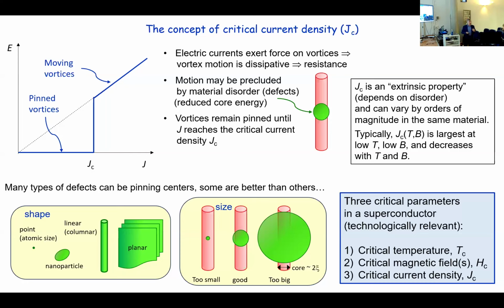The pinning of vortices is the name of the game to try to produce useful wires, because you want this critical current density JC to be as high as possible, meaning that your wire can transport as much current as possible without dissipation. JC can change by orders of magnitude because it depends on the material properties, but it also depends dramatically on what you put inside as disorder. So it's extrinsic.